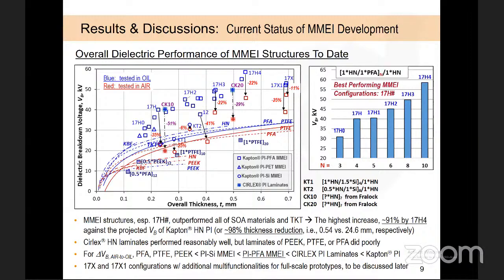As somewhat expected for its laminated structure, the Cirlex samples also performed quite well, but as a bit of a surprise, laminates of other semicrystalline polymers performed very poorly, which suggests different mechanisms. Another strength of MMEI structures was the low VB drop in air, less than Cirlex or Kapton materials.